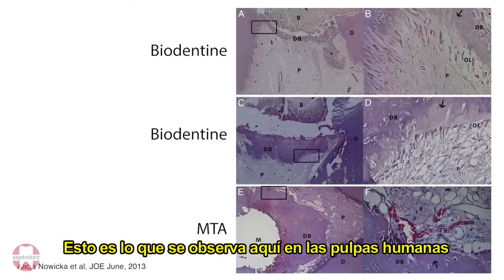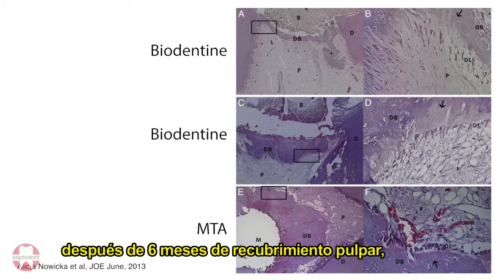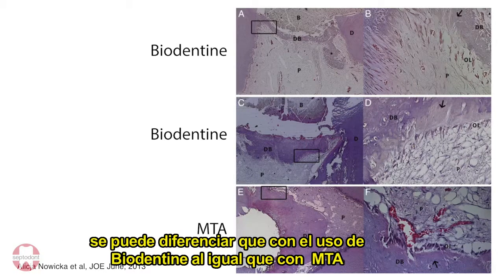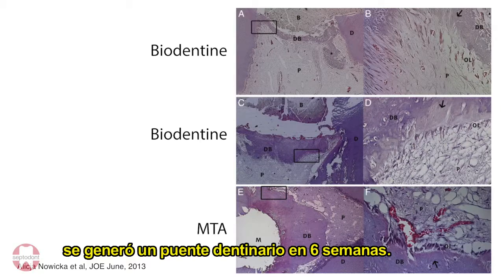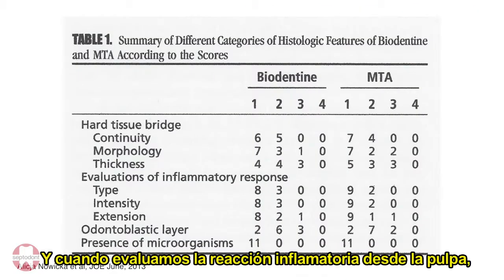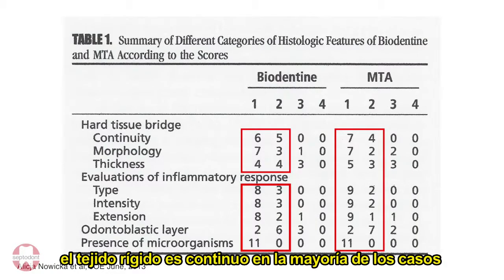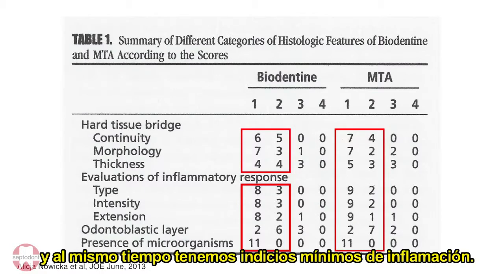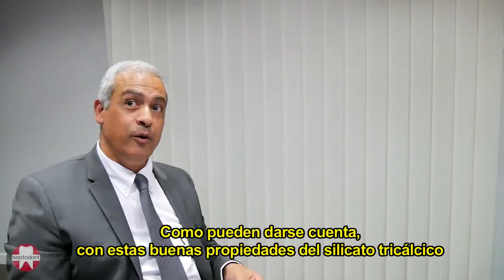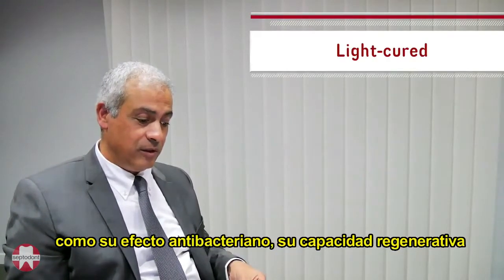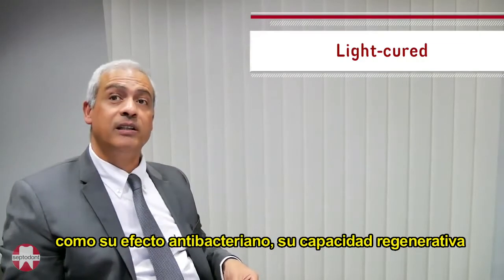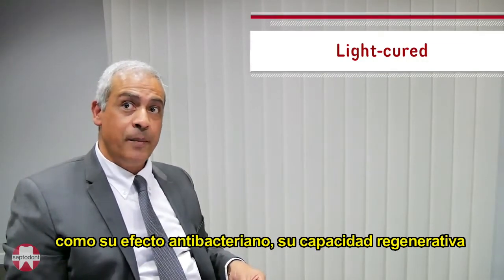This is what you see here in human pulps after pulp capping. You notice that Biodentine, in the same way as MTA, reproduced a dentin bridge in 6 weeks. When you evaluate the inflammatory reaction within the pulp, we notice that the hard tissue is continuous in most of the cases, and at the same time we have a very slight inflammatory reaction. So as you notice, with these good properties, tricalcium silicates are antibacterial and can induce regeneration.